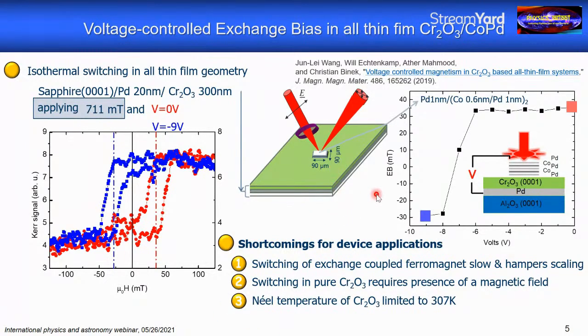And last but not least, the effect, as I said, requires the breaking of time inversion and spatial inversion, which both kick in below the antiferromagnetic ordering temperature, which we call the Néel temperature. Above it, you can't have this switching effect. And in chromia, that temperature is 307 Kelvin. So it is above room temperature, but only slightly. And for applications, in particular when you want to put these things in a CMOS environment, it's not high enough. So we had to increase the Néel temperature, and that was one of our first tasks.